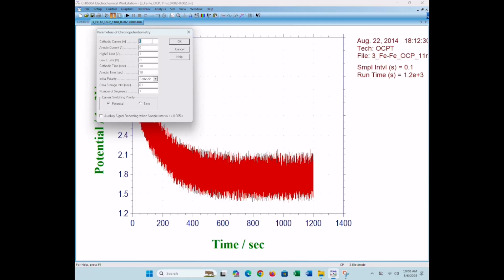For the iron-iron aqueous test cell, we used a cathodic and anodic current of 0.002 amps, a high E limit of positive 0.3 volts, a low E limit of negative 0.3 volts, a cathodic and anodic time of 1060 seconds, an anodic initial polarity, and a 3-second data storage interval. We ran 4 segments and used time as a current switching priority while keeping auxiliary recording off or unchecked. Again, because our resistance was so low, we kept these original parameters.